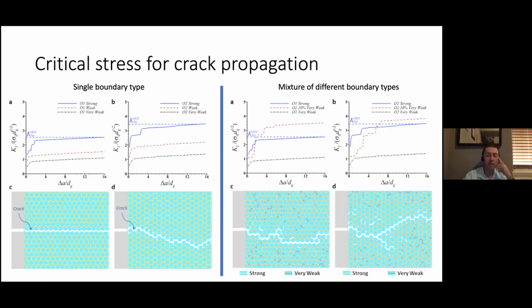And what we can see in all of these simulations is that the stress intensity initially goes up and then reaches an asymptote when the crack is ready to propagate in a fast manner, just run across the model. And so this asymptotic stress or critical stress is something that characterizes for us the toughness of the material, right? Or in other words, its resistance to fracture, if you will.